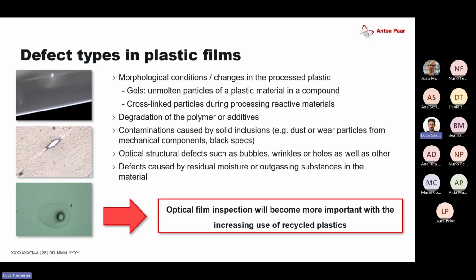Yeah, and this whole film quality inspection will become quite important with the increased use of recycled plastics. We see this especially whenever we do PET films. It's quite hard, as soon as it contains any recycled content, to get a very good film quality without any inclusions.